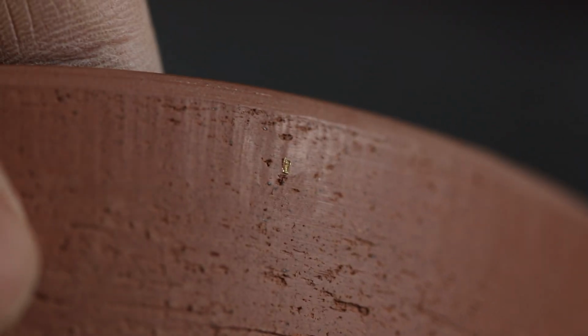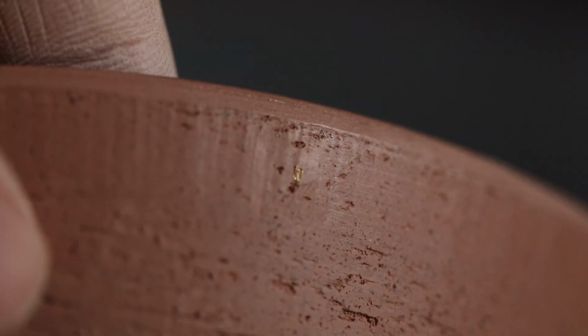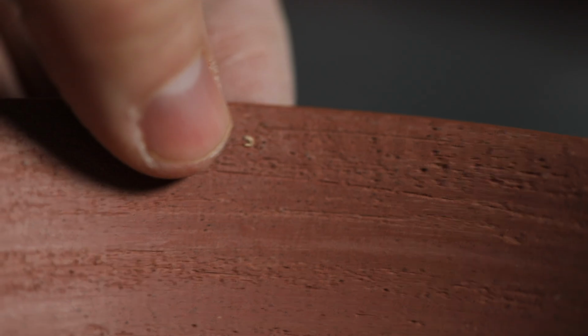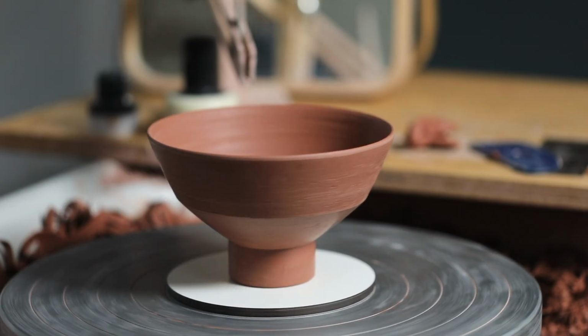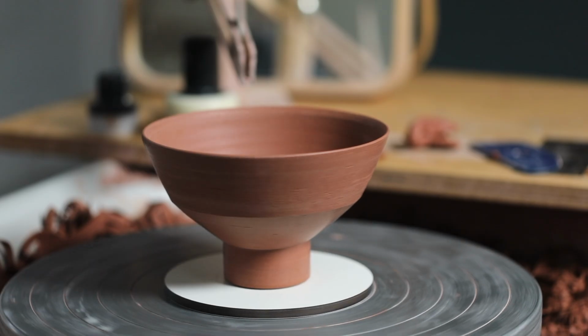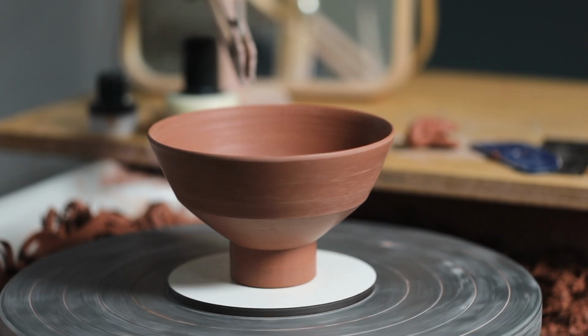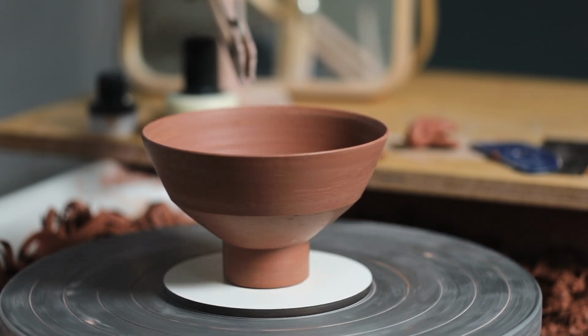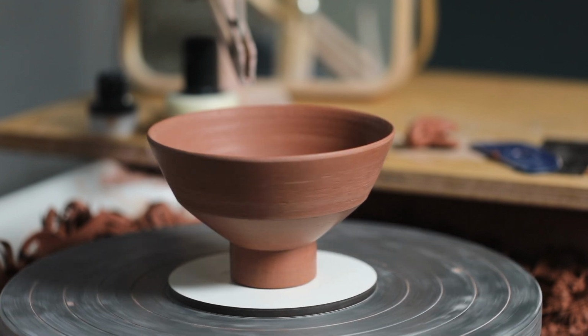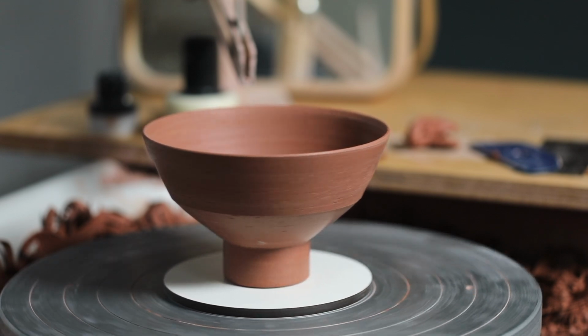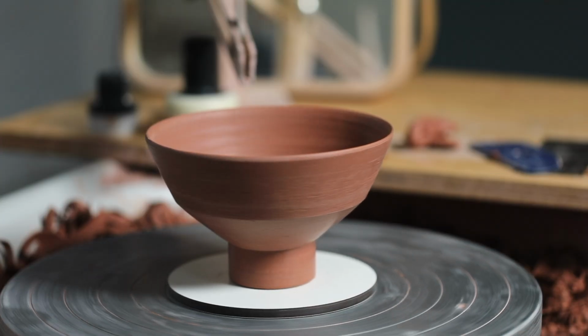That's all there is to it, really, and I'll use this time to quickly say that if you plan on doing this yourself and you don't have access to a gas kiln, your results will be very different from mine. The bronze and copper therein in this instance only turns red as I'm reduction firing using a gas kiln. With an electric kiln in oxidation, you'll get still relatively dramatic marks, but they'll be green, and they won't blossom quite so much as it does when fired in a reduction atmosphere. So just bear that in mind before you do this experiment yourself.